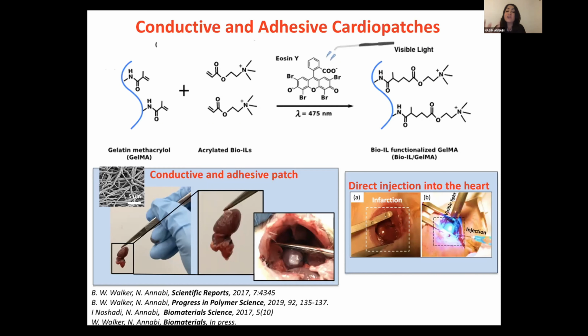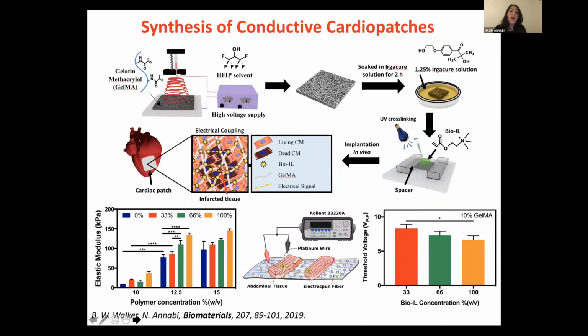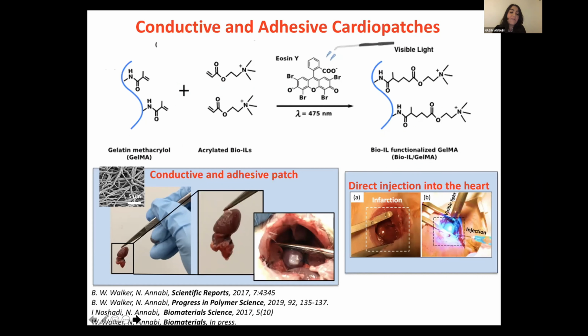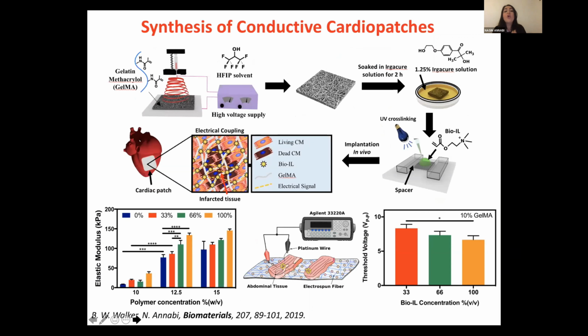So once we form this functionalized polymer, they can be used as an injectable formulation. You can directly inject them to any organs and cross-link it with visible light, or you can also use this formulation to form electroconductive and adhesive patches that can form as a prefabricated patch, and you can apply it on the heart after, for example, MI, to further improve the heart and have regeneration in the defect site. So I'm going to discuss a little bit about this approach that we recently published, and in this work we form electrospun sheet. We use electrospinning techniques, and we use a biopolymer as an example, GELMA. We form this fibrous structure based on GELMA.